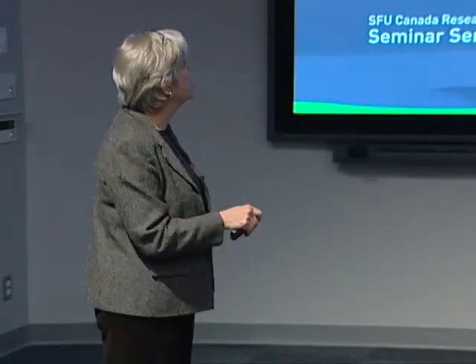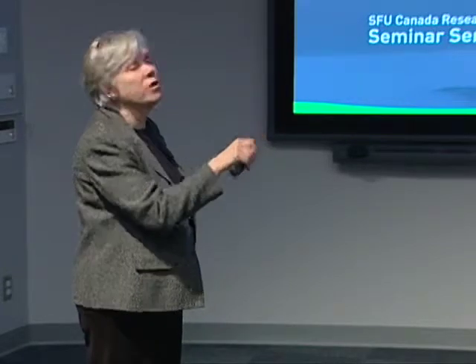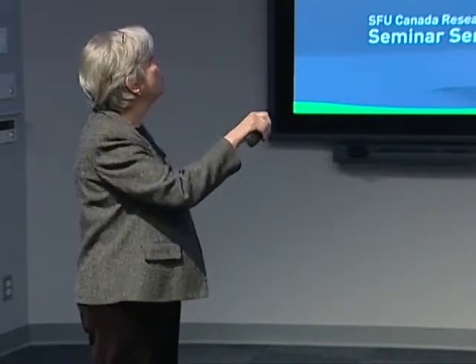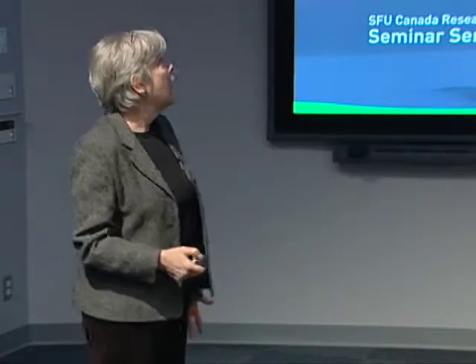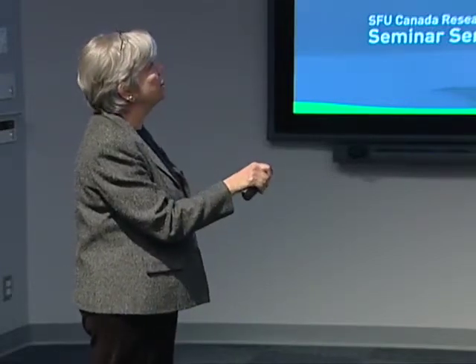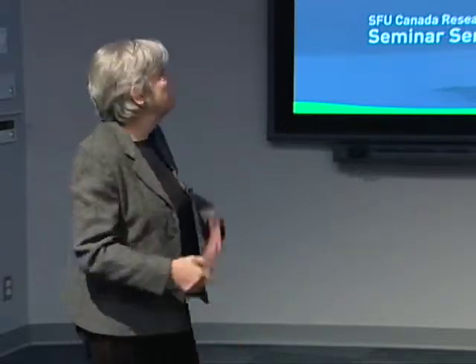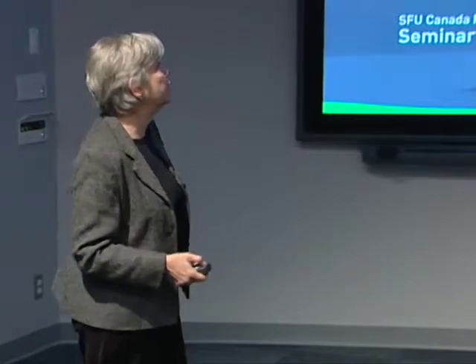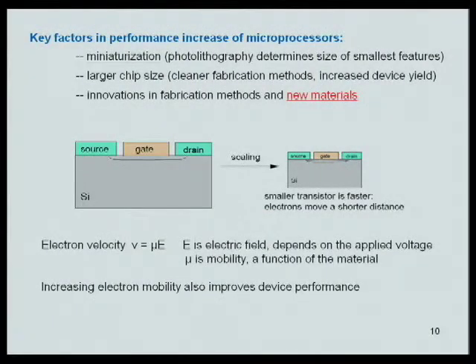Now, we can also increase speed by increasing this number, electron mobility. And we can do that by changing the material, getting rid of silicon, using something like gallium arsenide, which has a much higher electron mobility, or we can do this by modifying the material in certain ways. And in the case of silicon, the way that today's devices have been speeded up is by using strained silicon instead of just standard silicon.